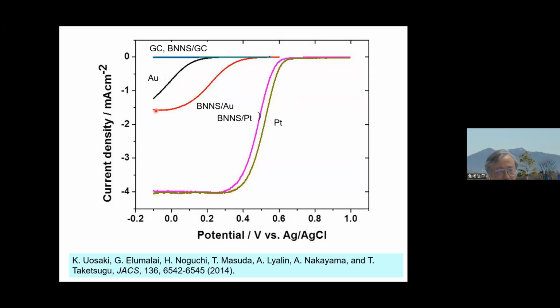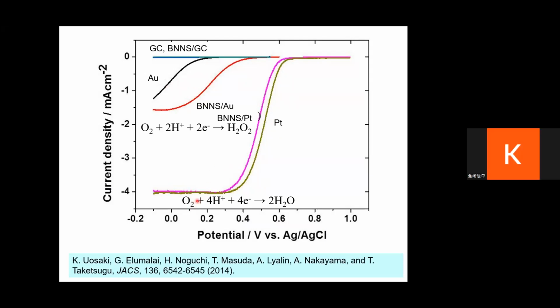Another thing you must notice is that this limiting current is quite small compared with platinum, because in the case of platinum, oxygen is reduced to water, 4 electrons. In this case, oxygen is reduced to hydrogen peroxide, 2 electrons. It's bad, but still it works.